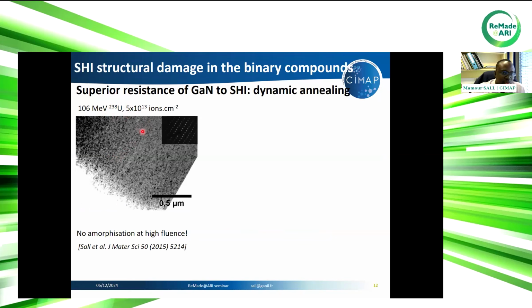In this case, we overlap the ions. I mean, all the ions. One ion will create an amorphous track. So as the tracks are amorphous, if we overlap all the surface of the material, if we irradiate the whole surface of the material, at the end the material should be amorphous because each individual track is amorphous. So if we overlap tracks all over the material surface, we should have an amorphous material. But this is not the case.